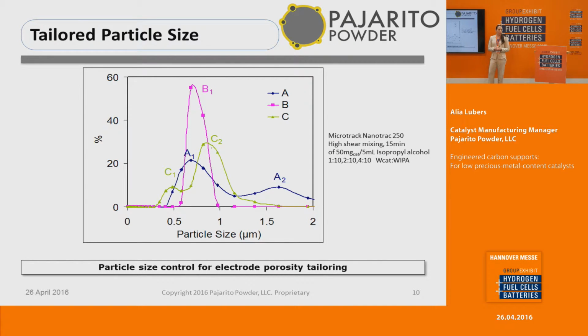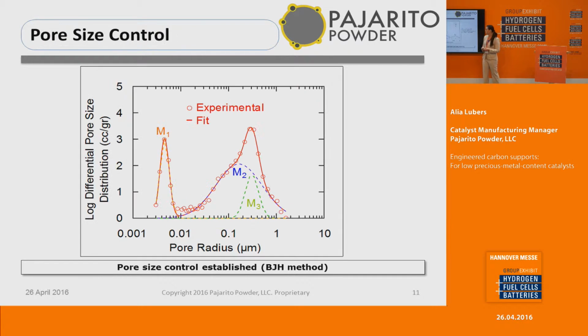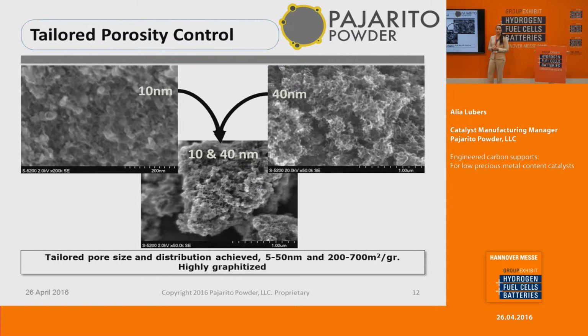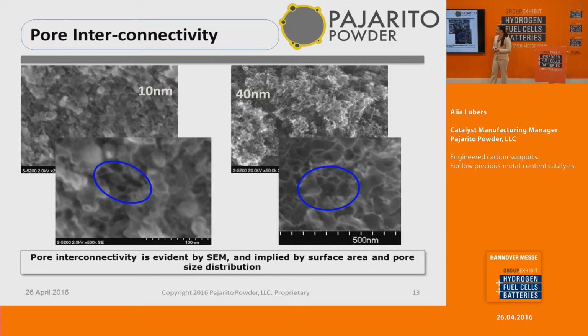Because of our synthesis process, we can actually tailor the particle size to the needs of the catalyst layer demands. Additionally, we can manipulate our pore sizes to optimize that three-phase boundary. So not only can we make 10 nanometer pores and 40 nanometer pores separately, we can make those in the same material. Our measurements show that our pores are in a highly connected network, so we can access all parts of the material and be able to place the ionomer and platinum in the best way possible to make this catalyst most efficient.